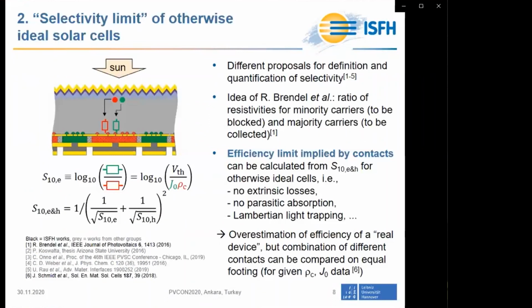Regarding the definition and the quantification of the selectivity, different proposals have been made. The idea of Rolf Brendel et al. was to define the selectivity of a contact. Let's consider here as an example this electron collecting n-type doped polysilicon and oxide contact as the ratio of resistivities for the minority carriers. Those are the carrier type which should not be collected by this contact, in this case the holes.